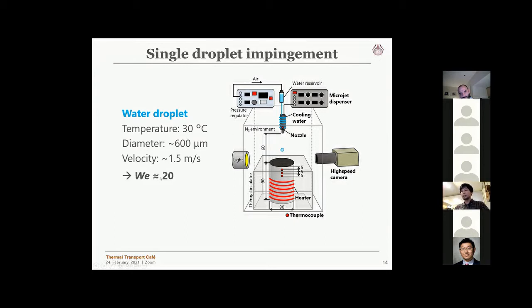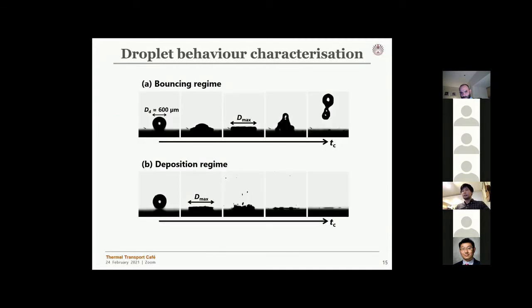In this experiment, we limited the Weber number to around 20. In reality there's a wide range of Weber numbers, but we limited this to make analysis easier. From this experiment, we looked at two different droplet behaviors depending on the temperature range. At higher temperatures, we observed a bouncing droplet.